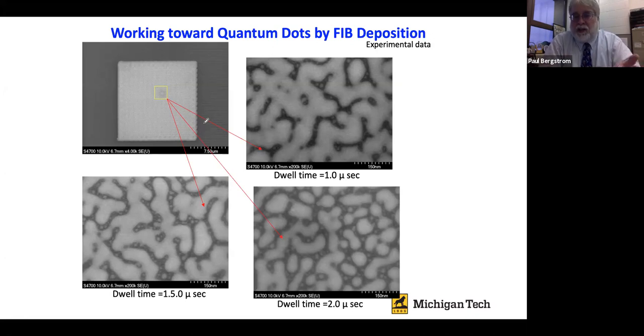And if we balance the amount of time that the focused ion beam sits in a certain pixel at a certain location, we can balance the amount of energy that is being used toward the decomposition of the gas, and the amount of energy that's going toward the actual etching of the substrate, etching of the underlying layer, or etching of that deposited layer, as the case may be. And so this was something that we noticed in some of these early images, where our deposited films were not continuous, where we had small nucleates of the material that were isolated from other regions, right?